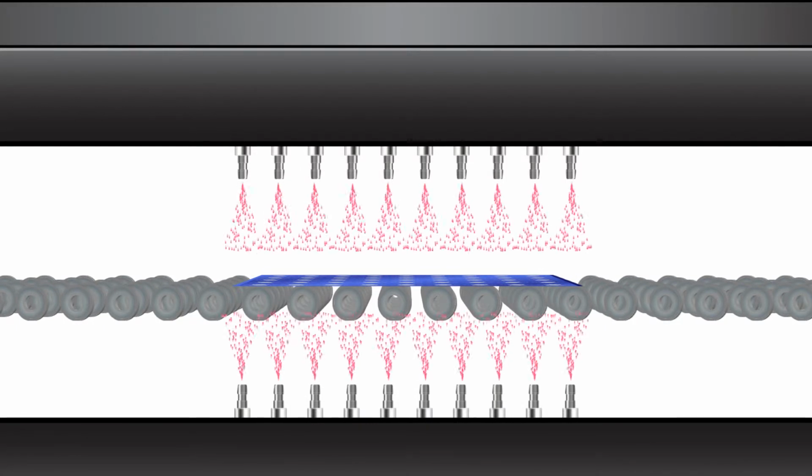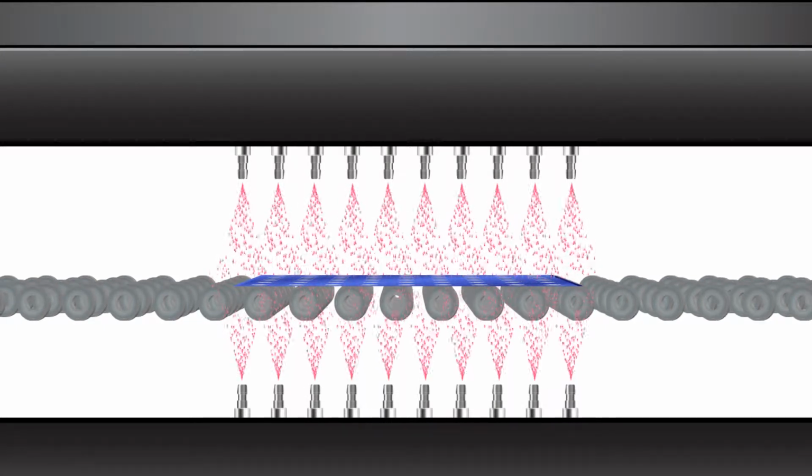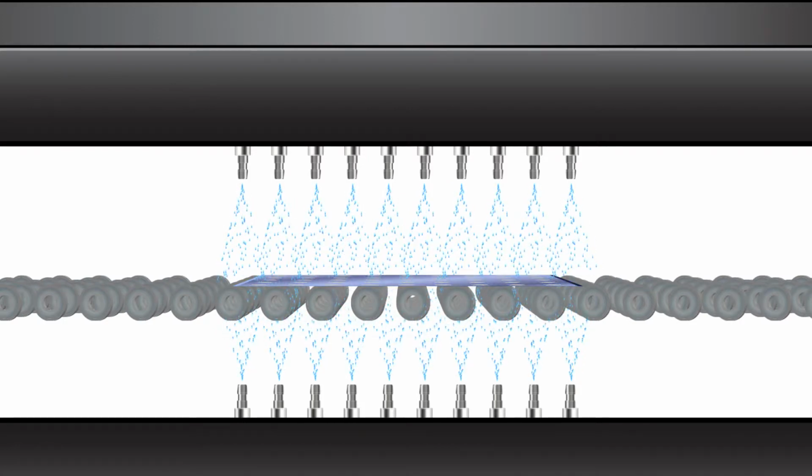etched. In the etching machine, conveyors carry the sheets through a spray chamber, where heated acid is sprayed at both the top and the bottom sides of the sheet. The unprotected metal is dissolved and rinsed away. In another automated line, the resist is washed away in a caustic solution, leaving pristinely clean parts.